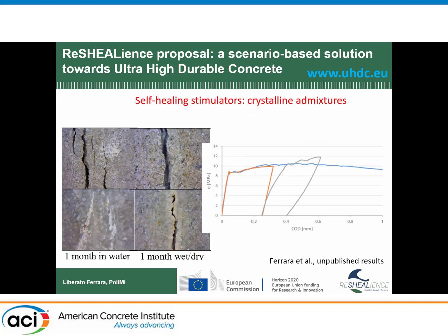And finally, to come to the self-healing, these are the first results that we obtained. This is a crack. It is about 100 microns wide. In 1 month cured in water, it is completely closed. 1 month wet and dry, well, it's partially closed, but it's natural.